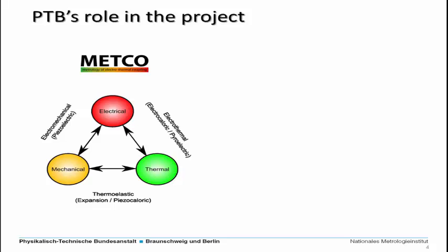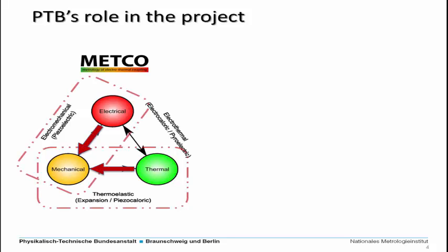You have this triangle of coupling effects in piezoelectric materials, and these two are under investigation in our experiments. So we are varying the temperature and also the electric field applied to the sample and determine the mechanical change of length of these material samples.